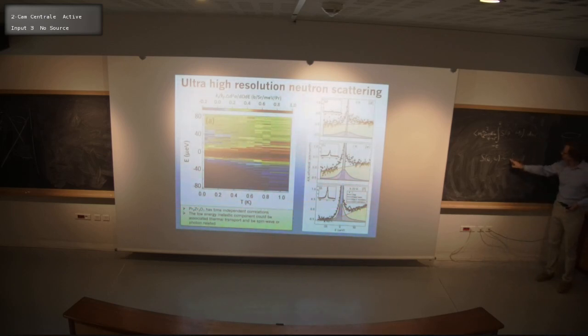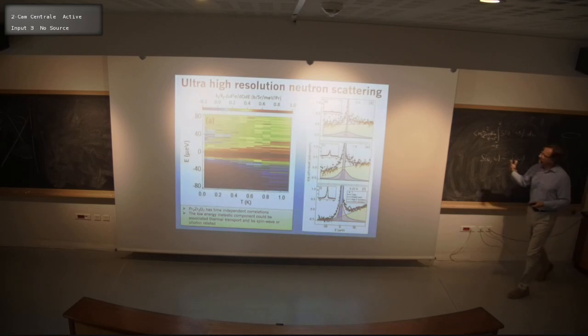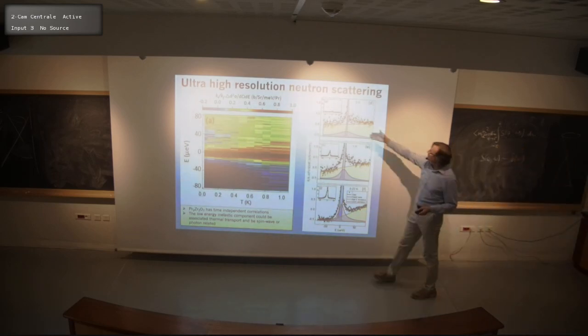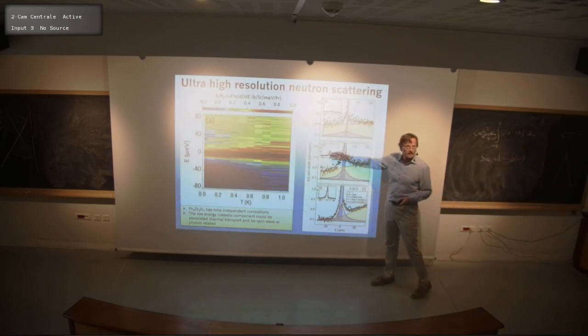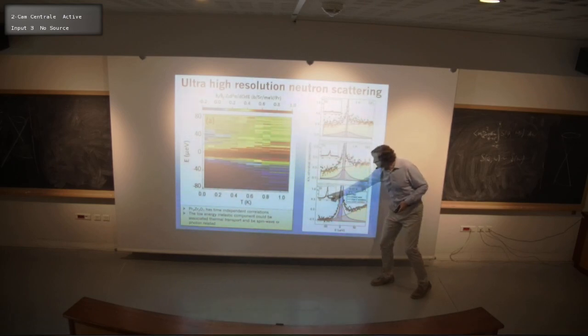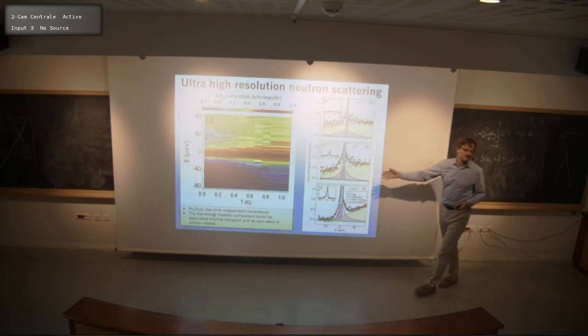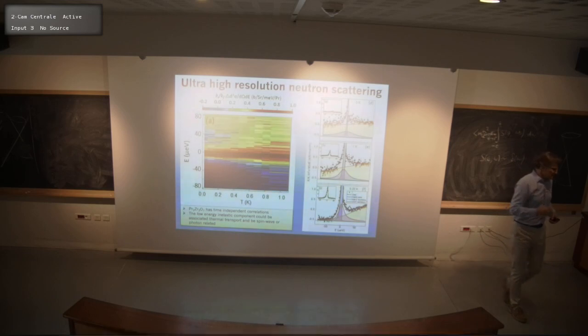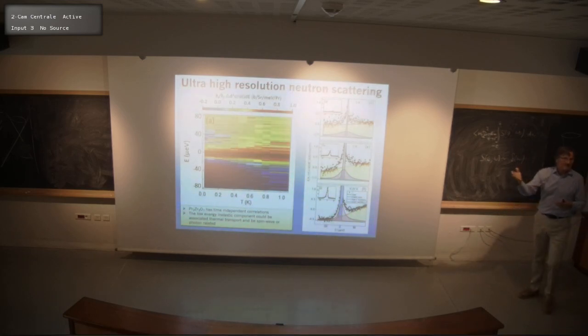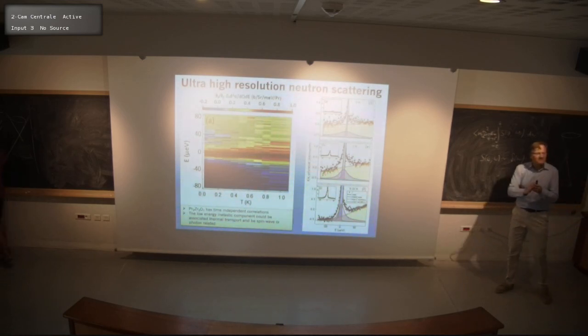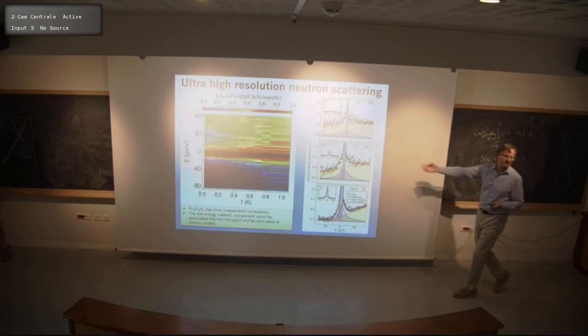And whatever thing I see in front of here becomes a measure of the strength of whatever it is that's frozen. So in this case, I know technically what the energy resolution of my instrument looks like, and I'm getting this peak which follows the known energy resolution of the instrument. So that means that I must have a delta function, potentially broadened up to what the resolution is.